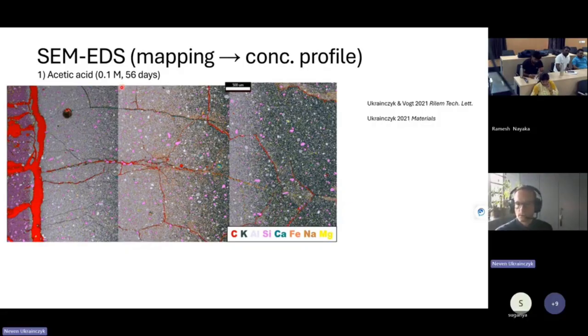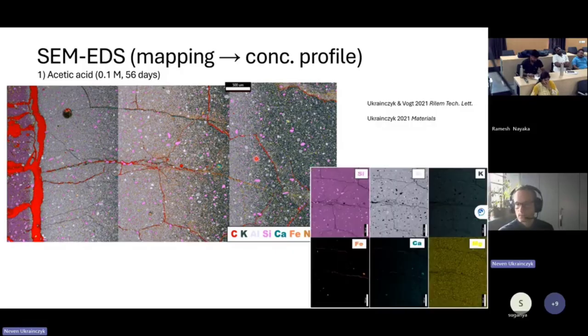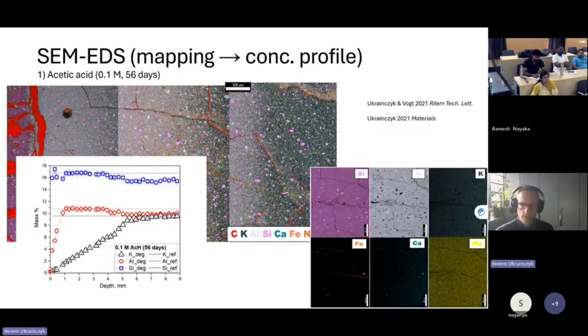And then you analyze, you take an area and then it gives you the chemical analysis of this area. So we have to do it manually per depth, and then for each window, we get the chemical composition by EDS for the smaller areas. It's similar to what we are doing for chloride ingress. This is the round robin test. But now here you can see it on the acid attack.